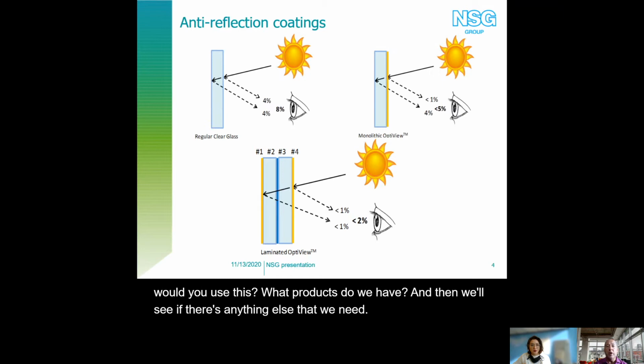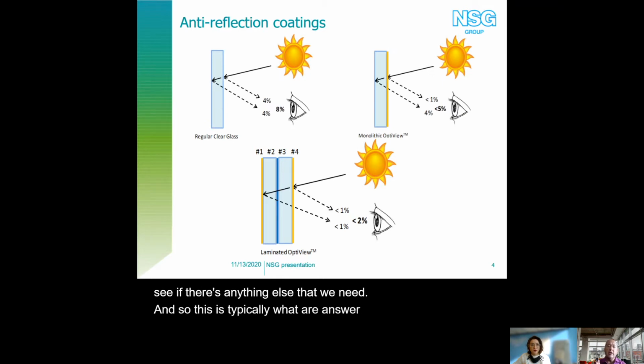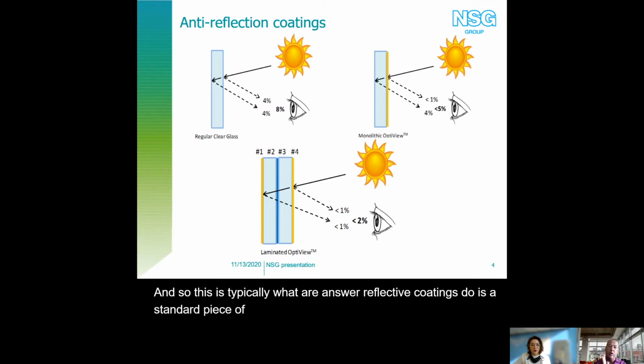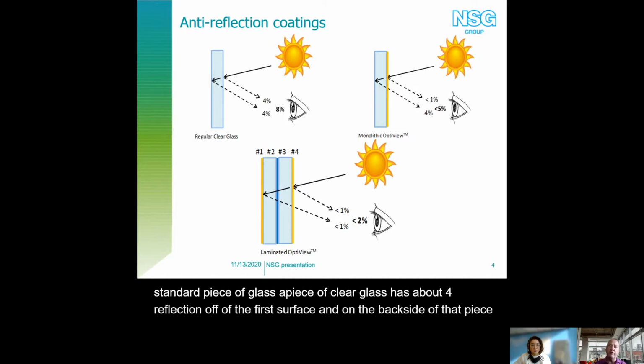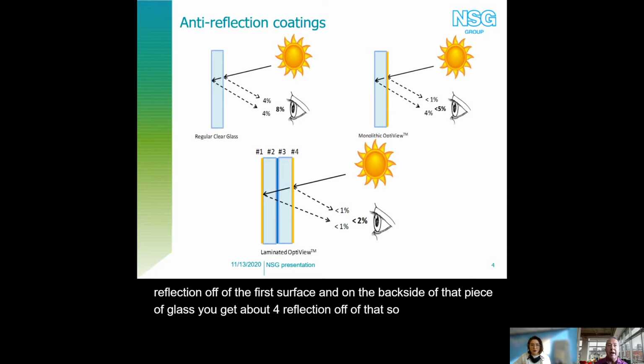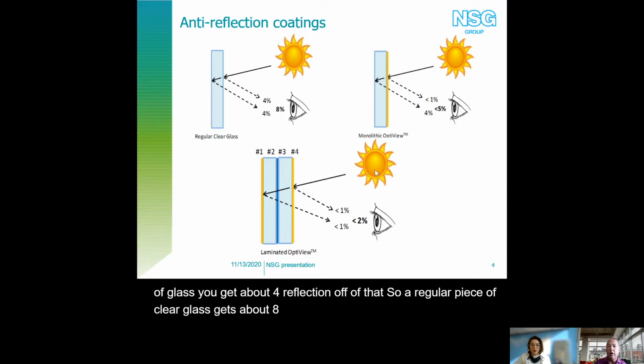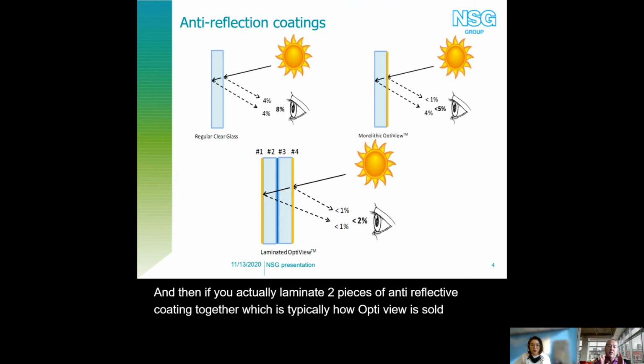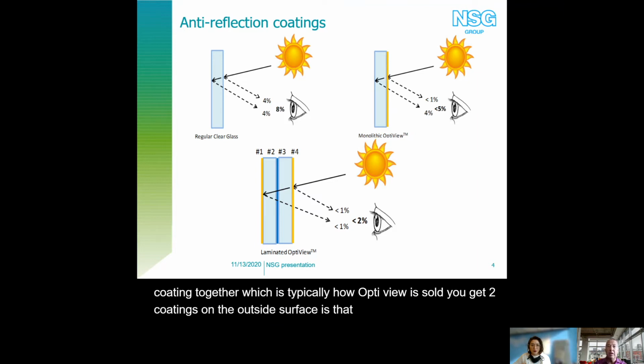Typically what our anti-reflective coatings do is this: a standard piece of clear glass has about 4% reflection off of the first surface, and on the back side of that piece of glass you get about 4% reflection off of that. So a regular piece of clear glass gets about 8% reflectivity. If we put a coating on there that's designed to be anti-reflective, you're reducing that 4% reflection down to less than 1%. And if you laminate two pieces of anti-reflective coated glass together, which is typically how OptiView is sold, you get two coatings on the outside surfaces, each less than 1%. So your overall reflectivity on that glass is less than 2%.